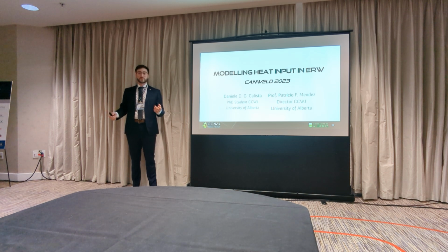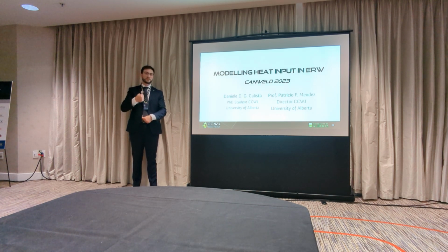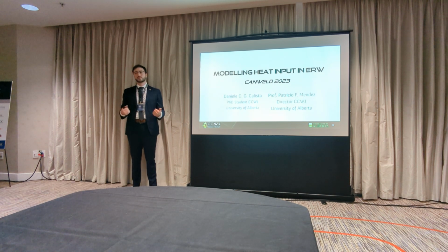So you can still produce penetrators, but now you're going to have to squeeze harder in the process, because the squeeze in ERW is meant not just to create a metallurgical bond, but also to eject any oxide films. That's why it's so difficult to understand how penetrators form, because industry says, okay, let's just keep squeezing until they push them out. But if you squeeze too much, now you don't have a circular pipe.